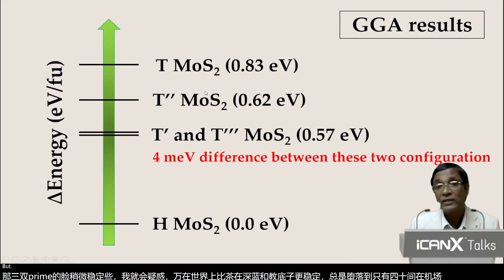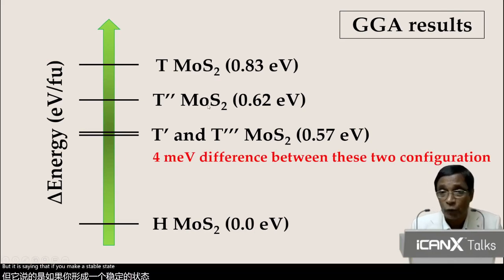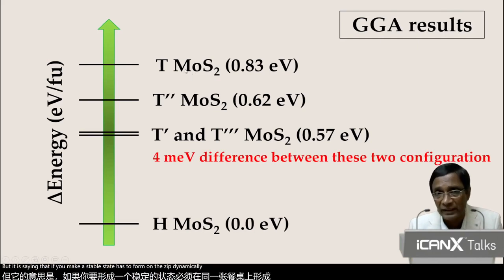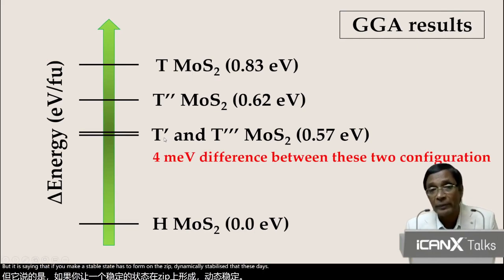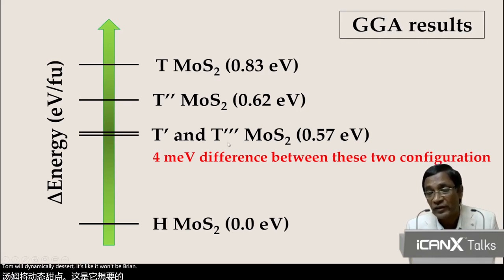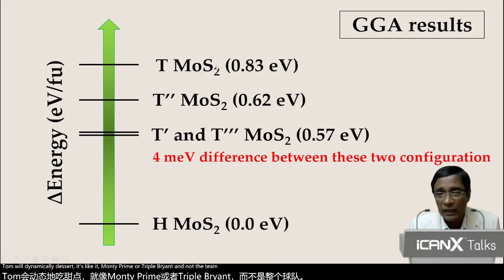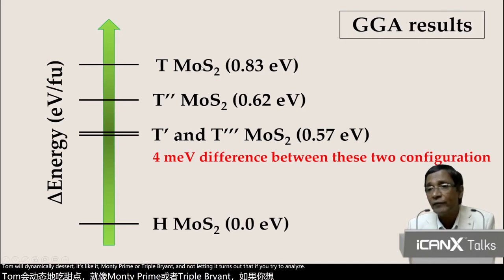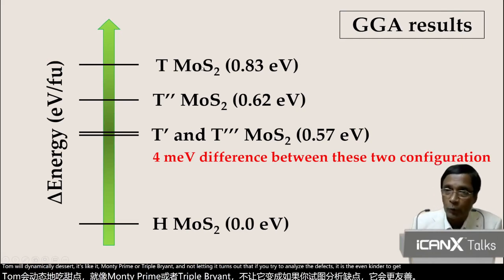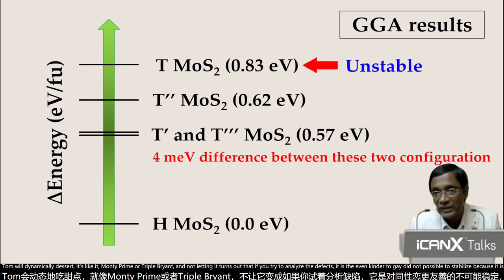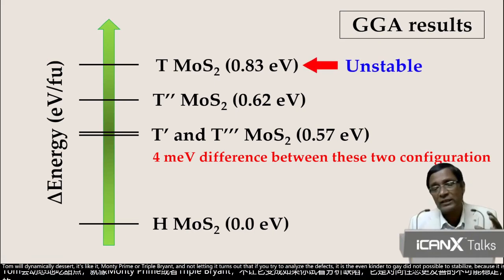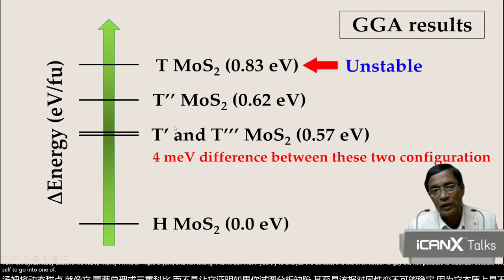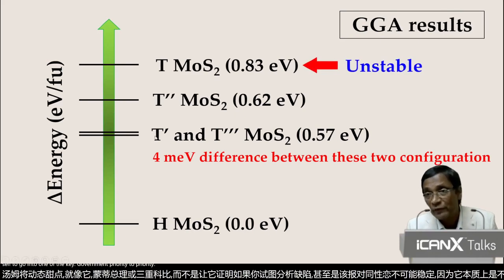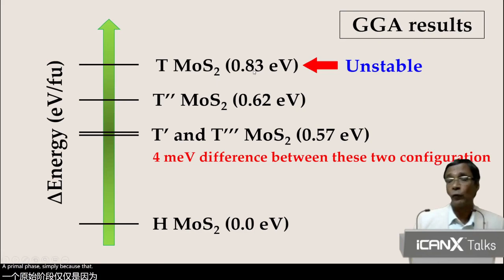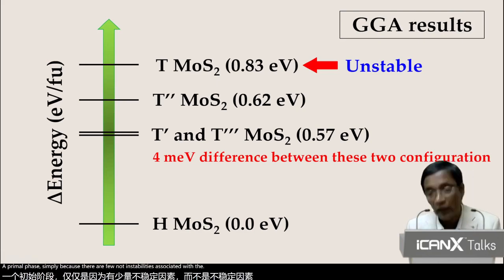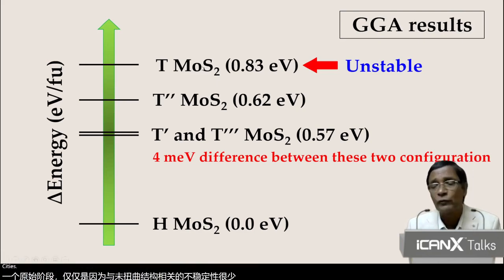But it is saying that if a metastable state has to form, unless I kinetically stabilize the T state, thermodynamically it's likely to form T prime or T triple prime and not the T. It turns out that if you try to analyze the T phase, it is even kinetically not possible to stabilize because it is intrinsically unstable. It will spontaneously distort itself to go into one of the T double prime, T triple prime, or T prime phase simply because there are phonon instabilities associated with the undistorted structure. So it is unlikely to form T phase.